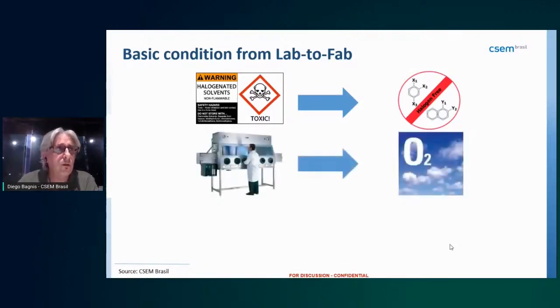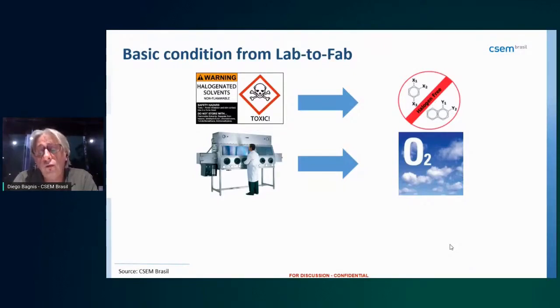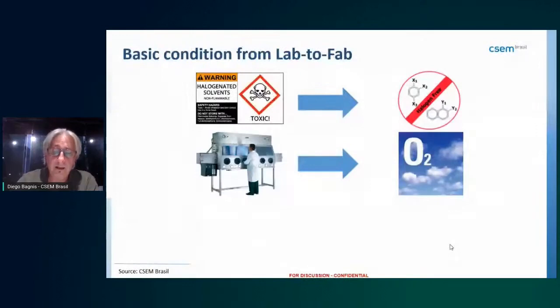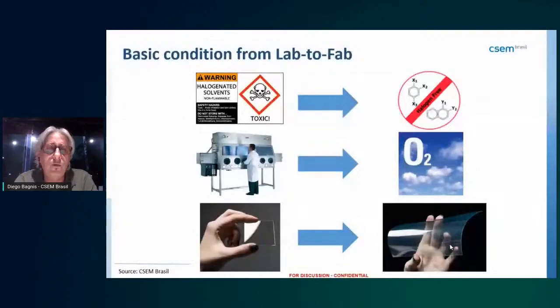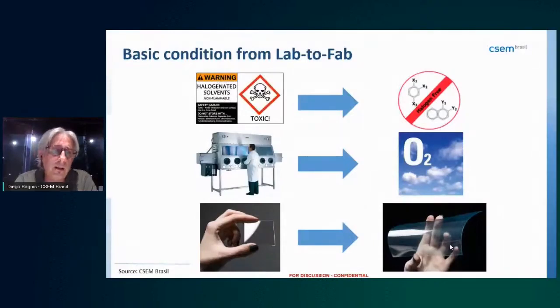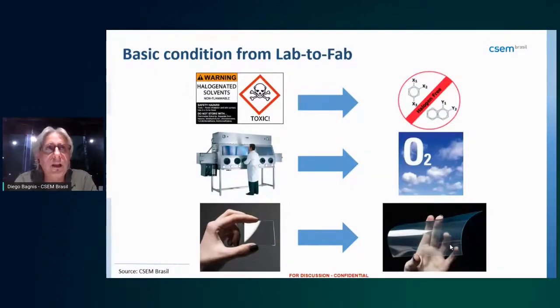The second part is to reduce capex for production — processing must be done in air rather than controlled atmosphere. The third part is to increase productivity and yield, which requires moving from glass to flexible substrates. For perovskite this may be a middle-stage possibility, but for OPV it is already a reality. The advantage of flexible substrates is a thinner, lighter film — typically on a PET substrate.